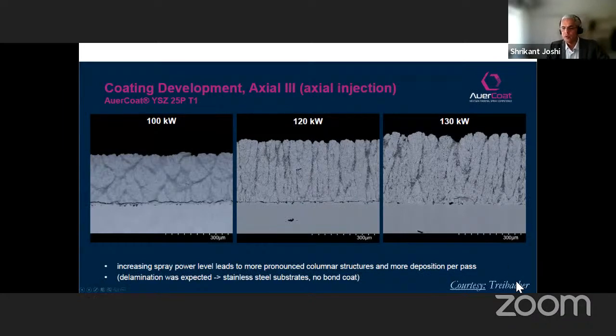A quick example from Treibacher about using an alternate non-flammable suspension medium. They've shown recently, for instance, that one could move away from ethanol, use a non-flammable, at the moment proprietary medium, and still get very good columnar structure. That's one. And the other thing that comes out from this particular slide, which is a reconfirmation of what I showed earlier, is that by increasing the spray power, one can get more pronounced columnar coatings and a higher deposition rate per pass. So good area to be in, the development of new suspension media, for example.